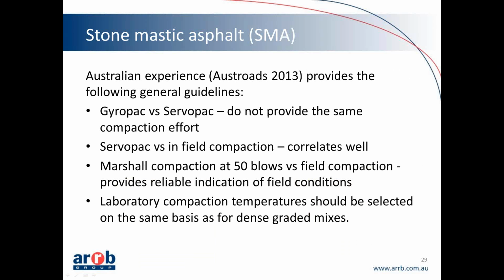Okay, what are these considerations? Just briefly, the Gyropac compactor is not really capable of achieving the same level of compaction as the servo pack, and that may lead to some unreliable results in the laboratory, especially when using a polymer modified binder and/or some active filler. Another outcome is that the Servopac provides the most reliable compaction with good indication of in-field densities, and also the Marshall compaction at 50 blows provides reliable indication of field compaction. So both compaction methods may be considered in the design.